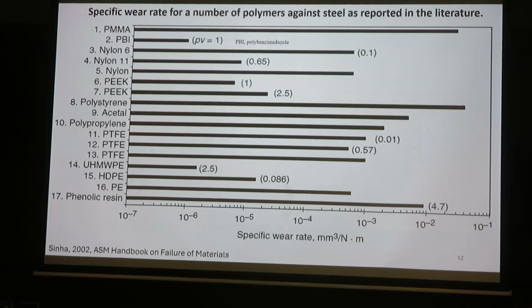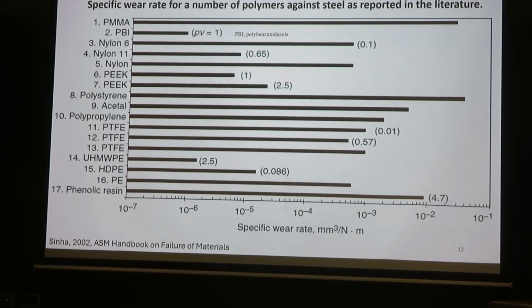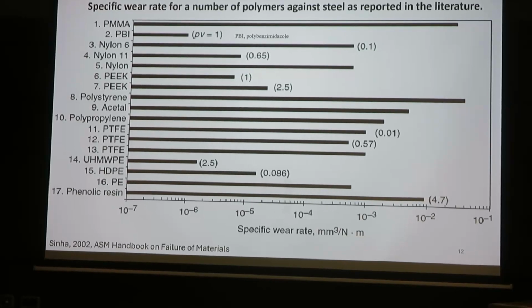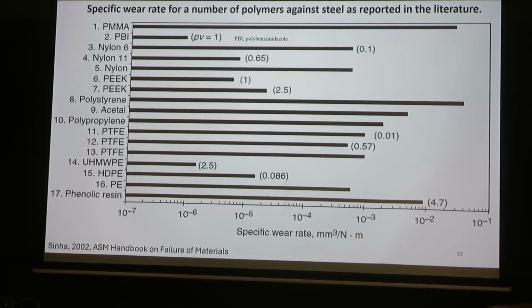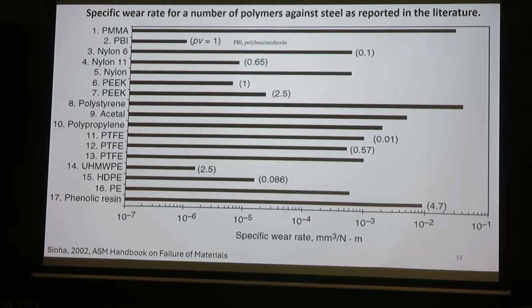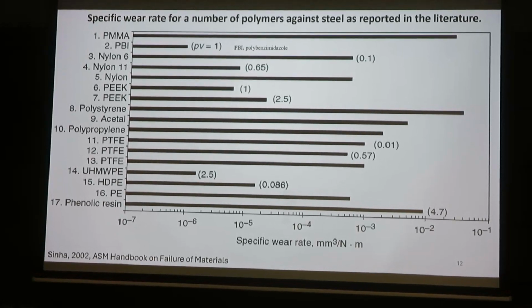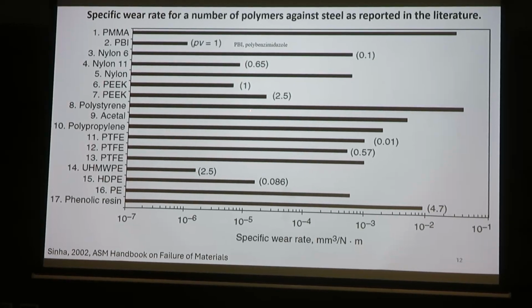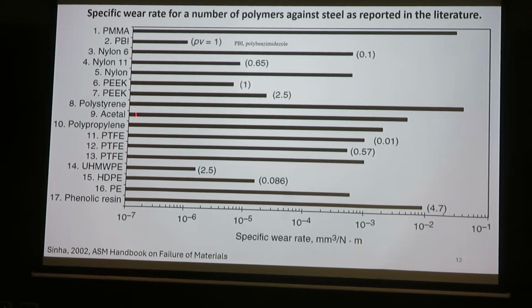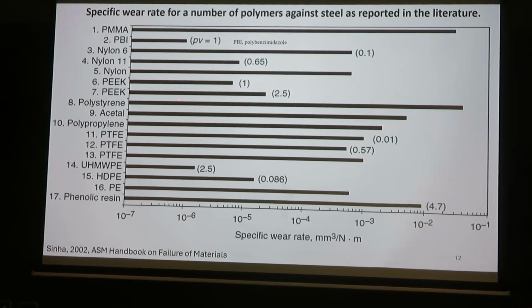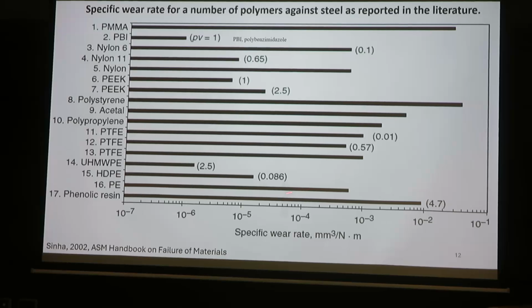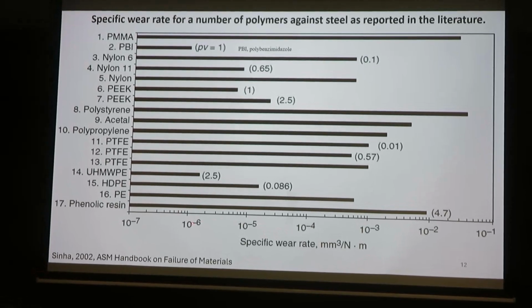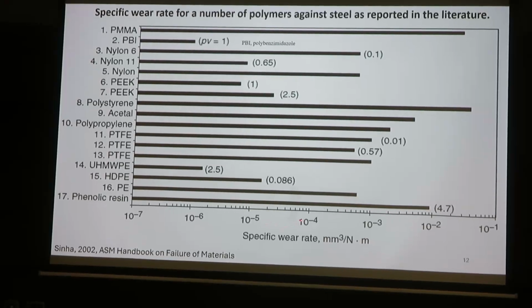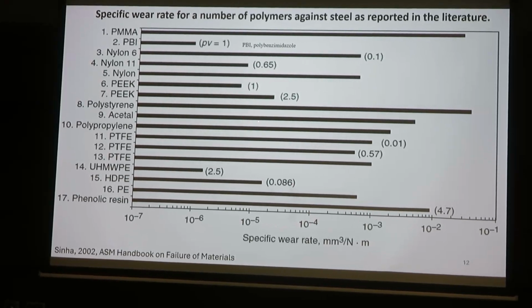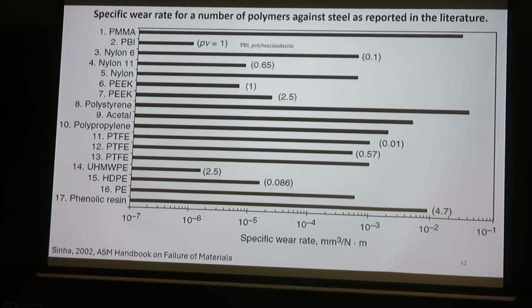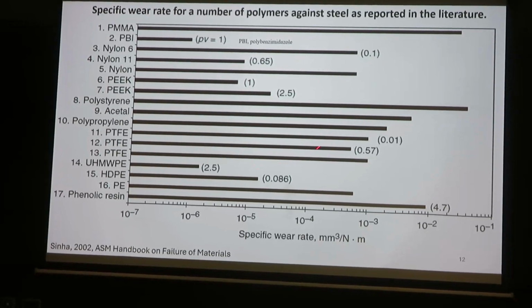So basically what it shows is that the friction and wear for polymers is very, very complex, and therefore we have to resort to experimentation, lots of experimentation, and see the trend. This graph summarizes from the literature values different pure polymers, these are not composites, and their specific wear rates. Normally you will see the specific wear rate is in the range of 10 to the power minus 6 to 10 to the power minus 4 for different PV values. Again, PV value is another important factor, and here these PV values are quite low.